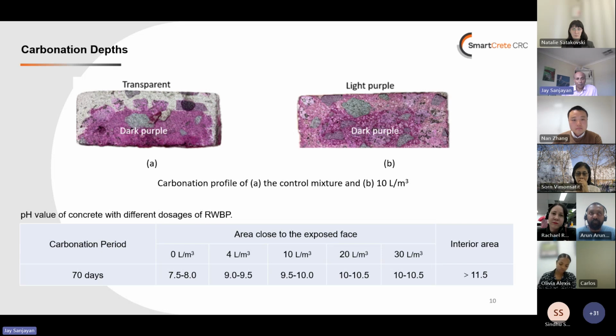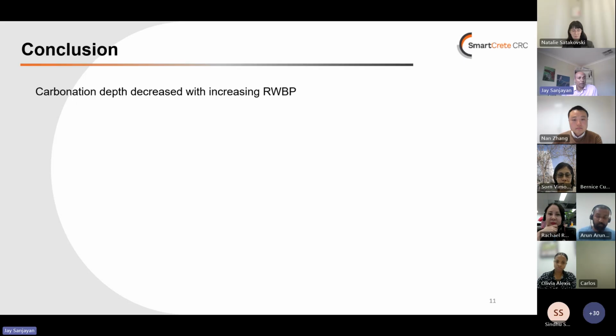But it's not as high as 11.5. 11.5 is what we have in concrete when it's uncarbonated. So there's a slight reduction of pH, but not as much as the normal concrete that's gone down to 7.5 to 8. So the pH is remaining high, but not at the same level as 11.5. So even though we say there is no carbonation, there's a slight reduction in pH, but it is not enough to cause corrosion of steel, I must say. So the carbonation depth decreased with increasing dose of paint. That is the conclusion from this part.